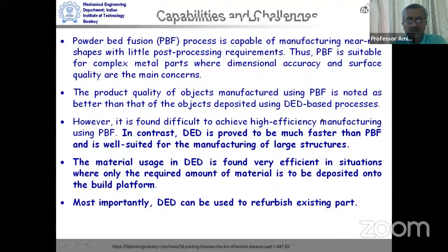laser-based DED processes. But the problem comes when we start talking of high efficiency processes. In particular, DED is proved to be much faster than PBF, and it's well suited for manufacturing especially large structures because its deposition rate is much higher. That's what we can do.